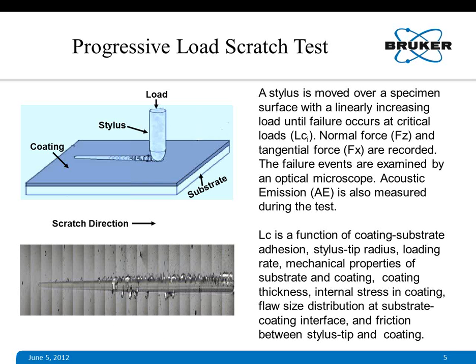Different types of failure modes may be present in a particular scratch test on a particular coating. We also measure other parameters such as acoustic emission or electrical surface resistance or contact resistance of this coating. The normal load corresponding to a particular failure mode is called the critical load, denoted as LC. There may be several critical loads for a particular system or scratch test, and that's why they are known as LC1, LC2, LC3, and so on.